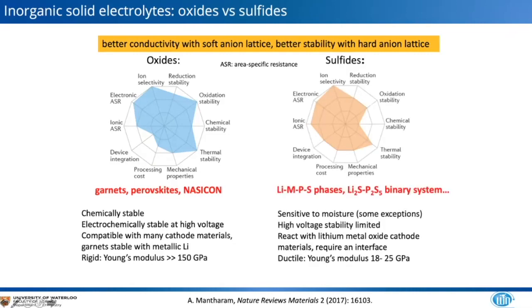Okay, so in the case of sulfides, a variety of different materials have been examined. These are sensitive to moisture, unlike the oxides. They have high voltage stability limits. They will react with the lithium metal oxide interface, which means that passivating layers are required, but they are relatively ductile with a low Young's modulus in the order of 18 to 25 gigapascals.